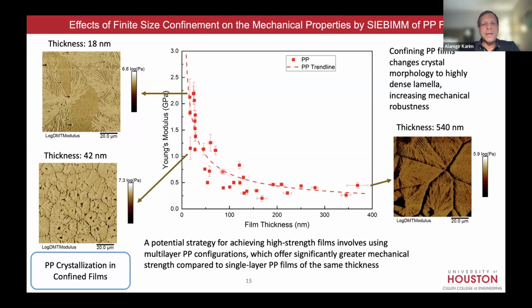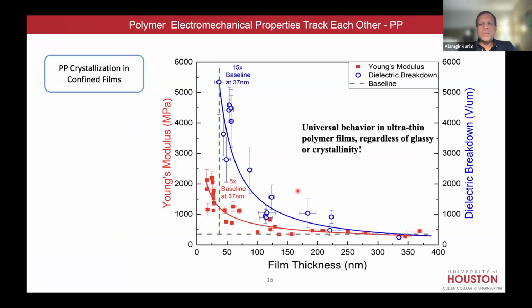All right, so this is the modulus enhancement. Then we measure the breakdown strength. That's the one of interest. Dielectric breakdown in blue with the modulus in red. And you can see the dielectric breakdown again goes up at 37 nanometer compared to 350. The breakdown voltage is 15 times higher than at 350. Since energy goes as the square of breakdown voltage, 15 squared would be 225. So basically, in principle, your energy storage in an ultra thin film is over 200 times that of the half micron film. Okay, energy density, that means per unit volume.